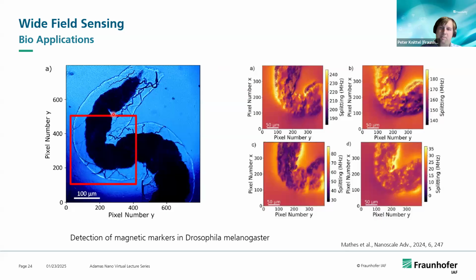And here, this was basically marked using magnetic nanoparticles. And what you see here actually on the right-hand side is the signal of these particles inside this intestine. So you basically have few nanoparticles visible. All of these maps here were taken from one orientation of the NV center. So all of these contain magnetic information, but from a different NV center, and thus gives you an insight in the complete vectorial field of the magnetic field that is imposed by these magnetic nanoparticles.